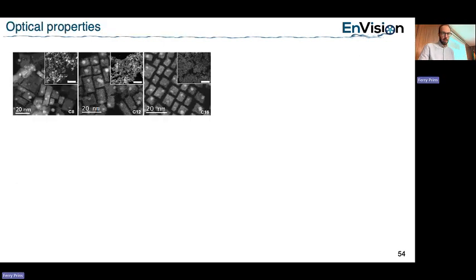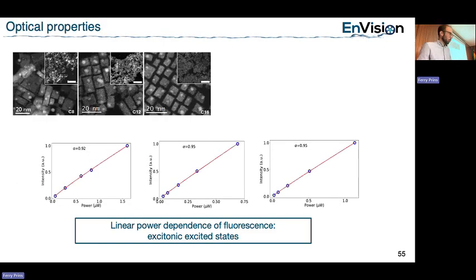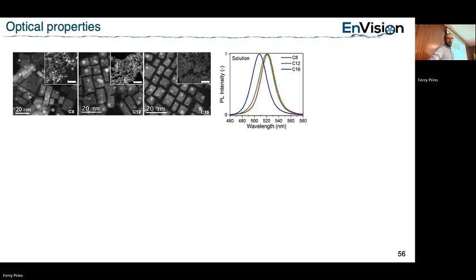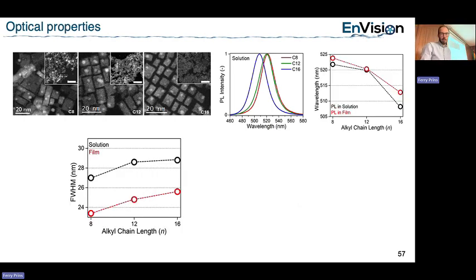Okay, so let's get into that. Here, linear power dependence - we're dealing with excitons. We can look at emission spectra in solution. We see there's a little bit of quantum confinement kicking in for C16 - the smallest particles have bluer emission than the other two. That's good, that's normal, that's what we expect. We see the same thing in the film.